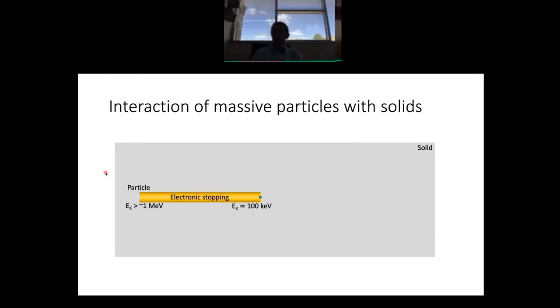When its energy is very high, the interactions with the nuclei in the solid, right? So the actual, what we think of as the actual atoms, is fairly rare simply because the cross section at high energy for those interactions is very, very small. So as this particle is losing energy to electronic stopping, eventually it gets down to an energy where the cross section for scattering from nuclei is relatively larger, and now it becomes possible for this particle to bounce off of atoms in the solid. And it displaces atoms in the solid from their original locations.